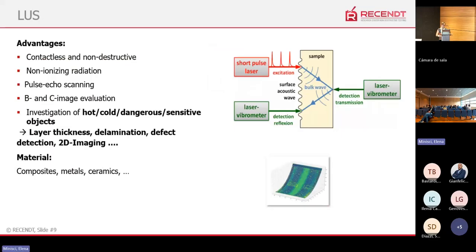At first, I will start with laser ultrasonic, which is a contactless ultrasound method where we use a laser for exciting and also for detecting the ultrasonic signal. It is based on pulse echo scanning, where we can make fast images in B and C scans. Because of the contactless behavior of this method, you can investigate at hazardous or dangerous places, really hot and cold materials, and also very sensitive materials. With laser ultrasonic, we can measure the layer thickness, the delamination, and detect defects in many samples.